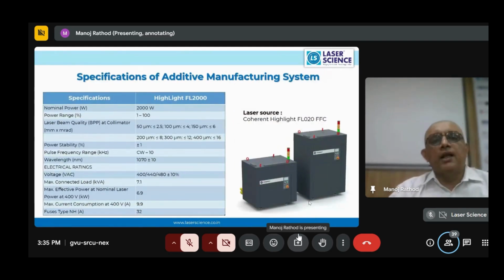Why we have selected this 2 kilowatt laser is because the beam quality of the laser from Coherent Incorporation which we have used is very good. You can see the wavelength is 1070 nanometer, and the beam BPP parameter is almost 150 micron. So very high beam quality. Pulse frequency, we can modulate from CW to 10 kHz pulse. Wavelength is 1070 plus minus 10. And this is a water-cooled laser, which is giving the highest power. So this is a multi-mode laser which we have used from Coherent Incorporation.